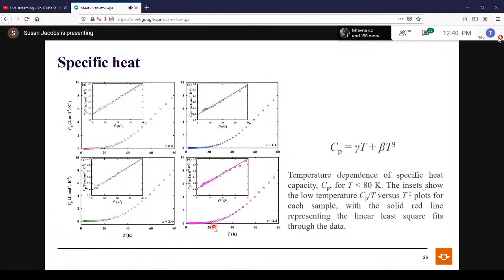Specific heat: we don't see transitions in Cp as a function of T. Chrome alloys don't show a transition for specific heat as a function of temperature, but there's still a lot of information we can gather from the low temperature specific heat measurements. So the dependence of specific heat on temperature is governed by this equation. Which means if you plot Cp over T versus T squared, then the intercept would give you the value of gamma, and the slope would be beta.